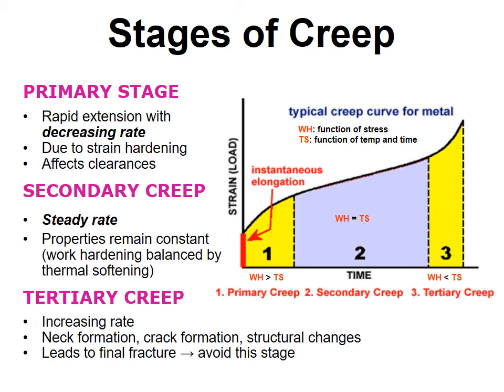Secondary creep then takes over. In this stage, the strain rate begins to stabilize and becomes constant and occurs relatively slowly when compared to the first stage and the final stage of the creep. This is because no microstructural damage has taken place yet, as work hardening is balanced out by thermal softening. During this stage, the grain size will also affect the strain rate, as metal with finer grains will creep faster than metals with coarser grains.